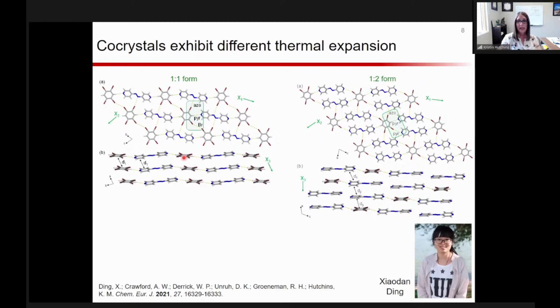And then the pi stacking is also different between the 2. In the 1-to-1 form, we have sort of perfect homogeneous pi stacking where all the tetrabromobenzenes line up and all the pyridines line up. But in the 1-to-2 form, we actually have quite a bit of different pi stacking. We have sort of 2 pyridine rings from opposite ends that line up, pyridine rings that are aligned lining up, and then a pyridine with tetrabromobenzene.